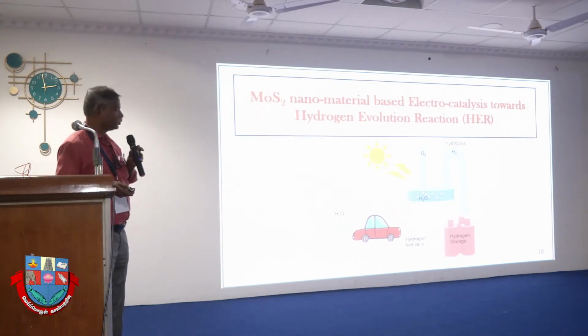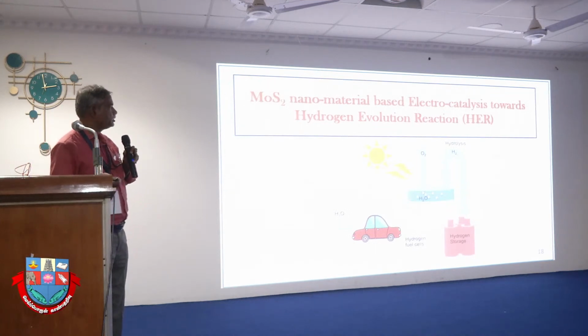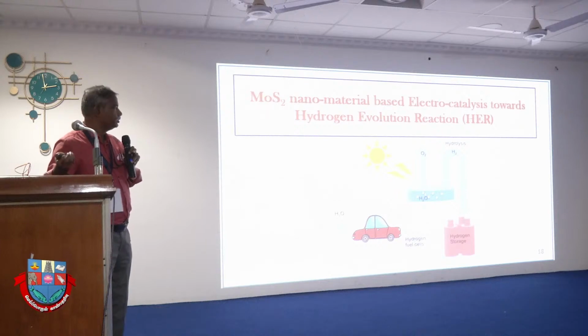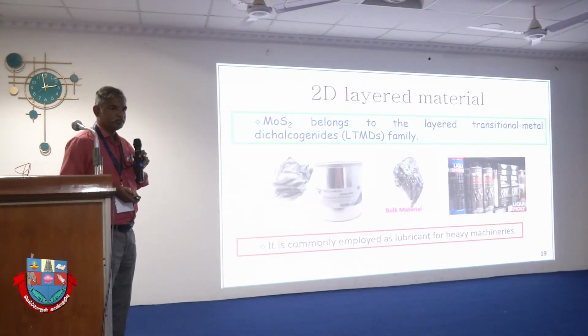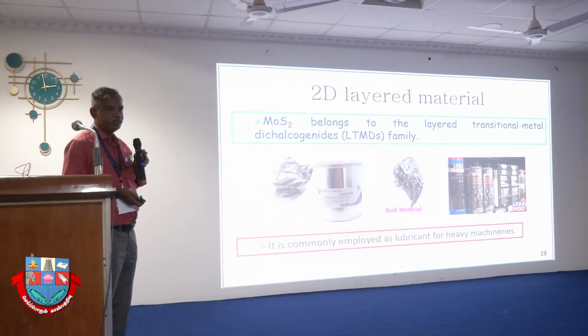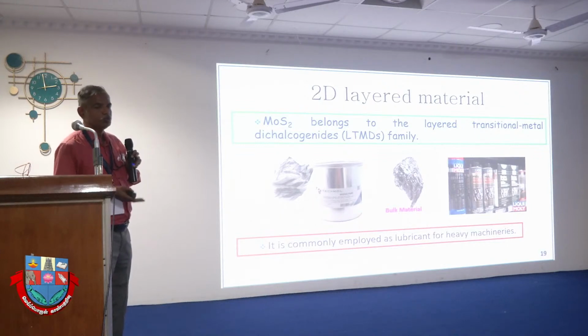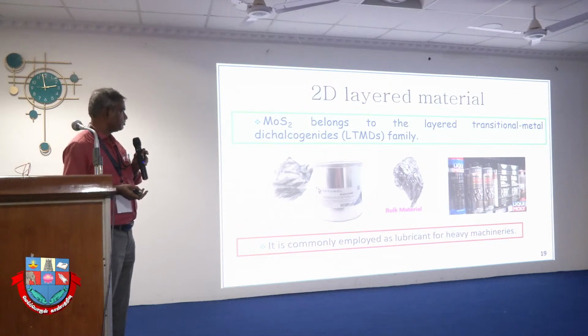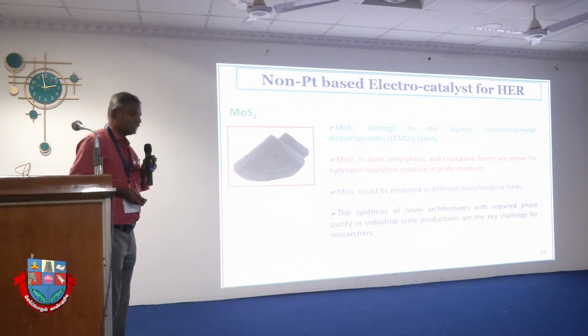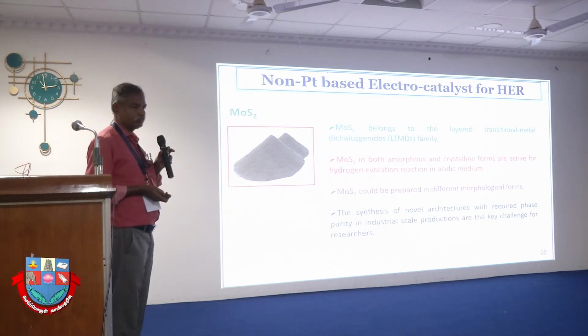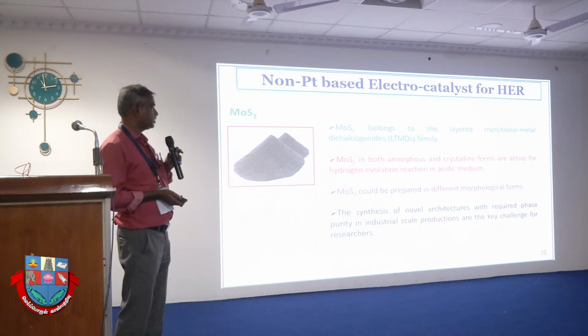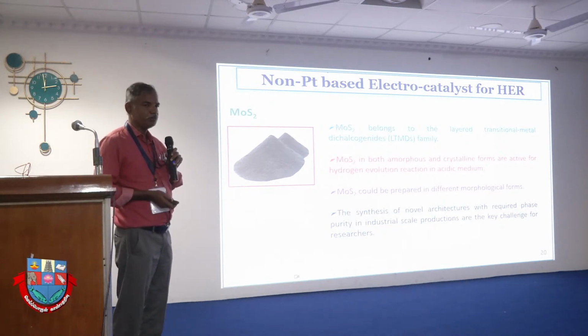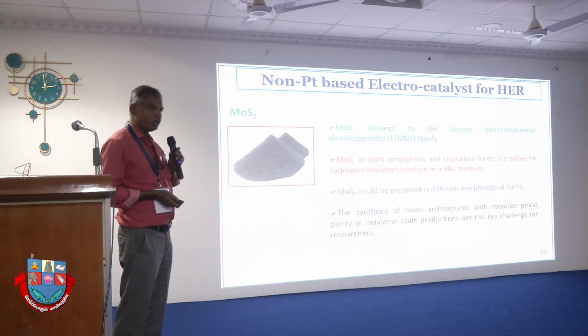So in the first phase, I will show you a non-noble metal MoS2-based electrocatalyst for hydrogen evolution. In industry it is called molybdenum sulfide. It's a very well-known lubricant used in heavy machinery. Now it's a layered chalcogenide material. MoS2 belongs to the layered transition metal chalcogenides. MoS2 in both amorphous and crystalline forms is active, because people have been working on it for almost 10 years. Both forms are active, but the stability is different, because amorphous will sometimes be more active than the crystalline form, but stability may be different.